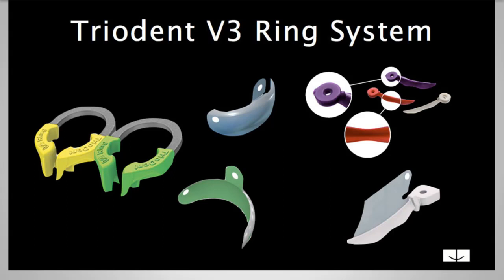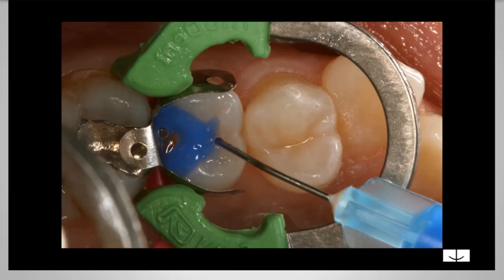All right, going back. Here we're into bonding. This is, you can see, what's called a full etch. So I'm putting phosphoric acid all over the tooth surface and etching the entire tooth. Once that's done, I like to go back in and re-wet my tooth to make sure it's at the optimal wetness. And I usually do that with a chlorhexidine solution.